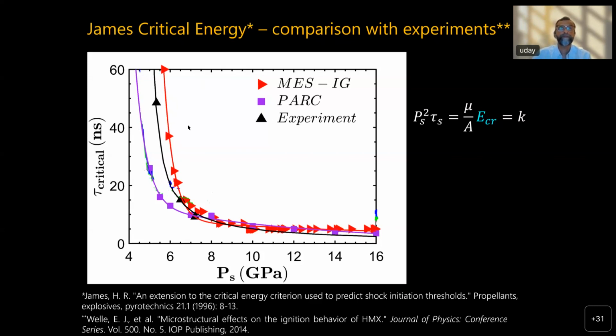This curve that I'm showing, even for MES-IG, can move all the way out here with one reaction chemistry model, and all the way to the other side with another chemistry model. And we found that, in fact, doing an inverse analysis, the best fit to the experimental data from the chemistry models comes from the Henson one equation global kinetics model. So that also plays a role, clearly, the chemical kinetics, because the temperatures here, due to void collapse at lower pressures, tend to be borderline. So the reaction kinetics model is very sensitive in that region in predicting the criticality.